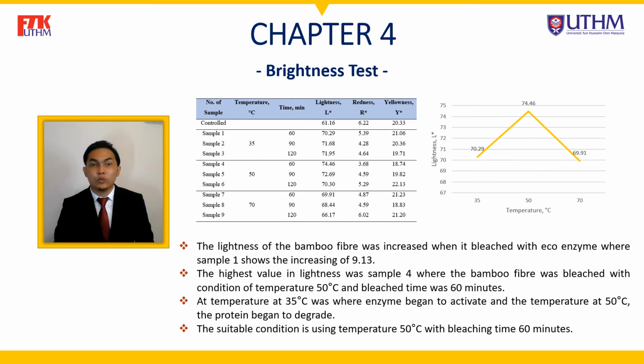The highest value in lightness was sample 4, where the bamboo fiber was bleached at a temperature of 50 degrees Celsius and a bleach time of 60 minutes. From that, it showed that the ecoenzyme helps in increasing the brightness of the bamboo fiber with the help of temperature, but the value of lightness starts to drop from sample 5 to sample 9 when the temperature and time increase.